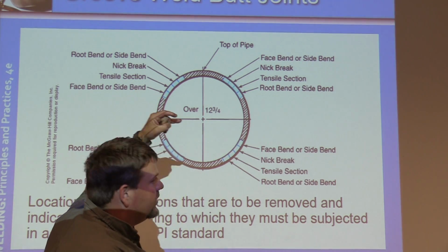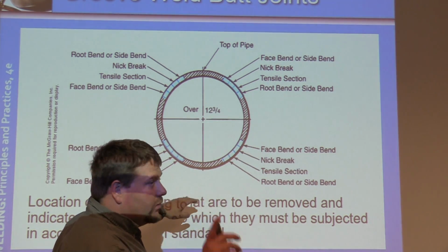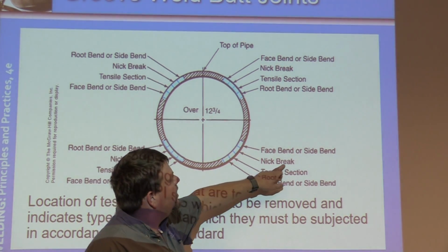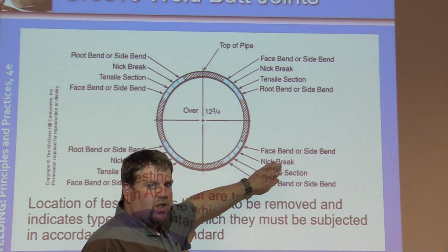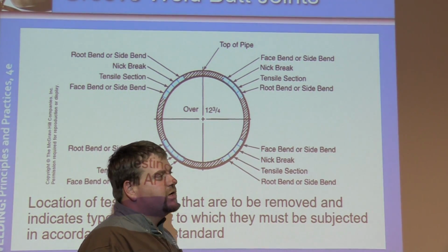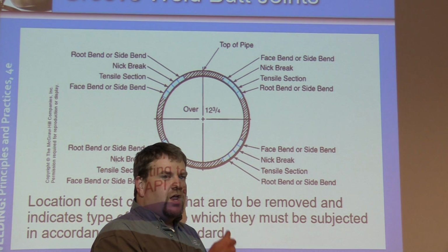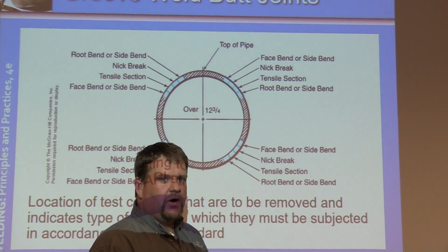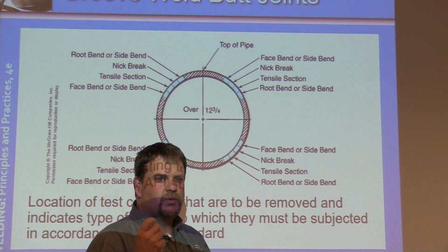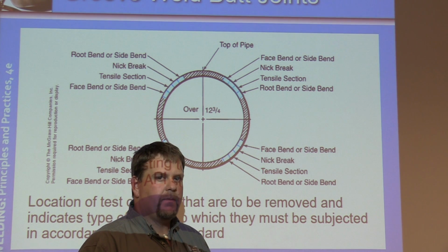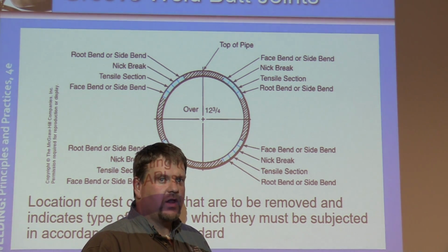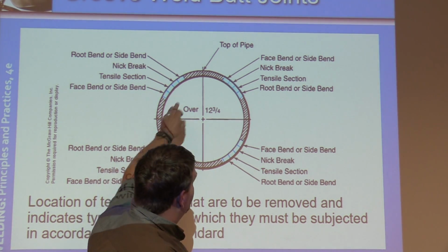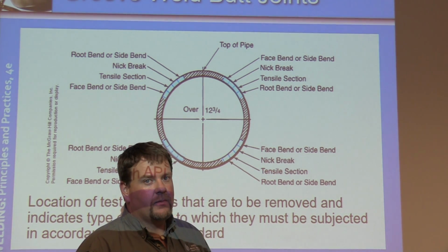2, 4, 6, 8, and twice as many, sorry. We're getting to it though. Now this right here, this nick break, this is specific to an API 1104 alone. So we put a nick in the center of the weld, and we pull it apart to see if the internal parts, specifically slag along the hot pass, are present within that weld. So now we just picked up 4 more tests, right?